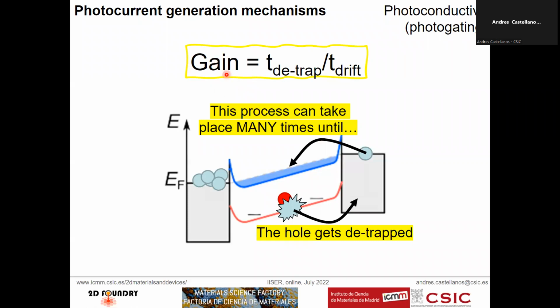Therefore, basically, this photogating mechanism has a gain. So you generate plenty of electrons per photon. And basically, this gain can be given by a ratio between the detrapping time, so the time this hole can live in this trap, divided by the drift time, the time it takes 1 electron to jump and go to the other electrode. Usually there are several orders of magnitude between these two times. Therefore, you get thousands of electrons per photon. That explains why these two-dimensional materials have 1000 amps per watt.